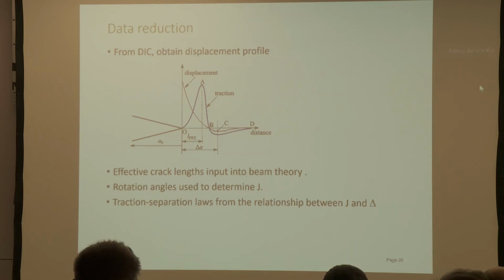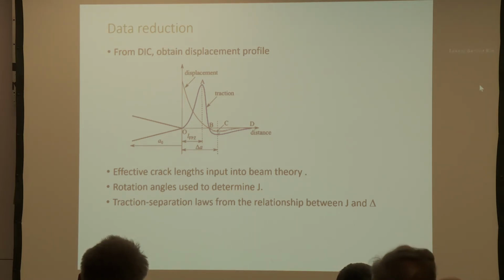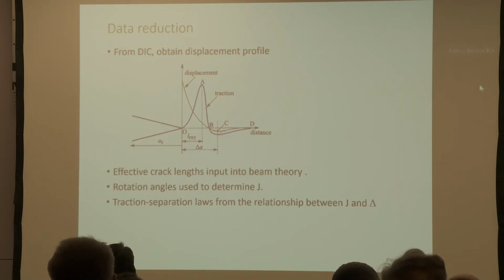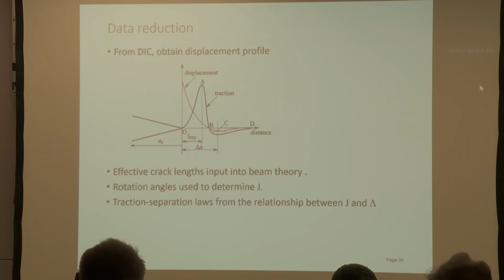But of course, there is a problem with that, and that's that at point A, or certainly at point B, you would have a zero displacement, but you would not have a zero slope to the displacement. And we've looked at different ways of defining this effective crack length, and the best scheme that we've devised is to take the position C, where the slope of the displacement is zero, despite the displacement not being zero. So we're defining an effective crack length here via a delta A term, which takes us to point O to C. And the rationale for doing that is that the slope of the displacement is much more important to the compliance. So the compliance has a higher sensitivity to that than it does the displacement.